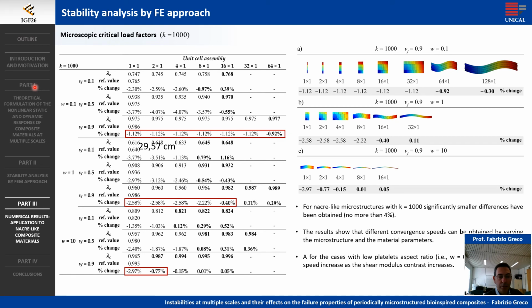For nacre-like microstructure with K equal to 1000, significantly smaller differences have been obtained. The results are reported in this table and show that different convergence speeds can be obtained by varying the microstructure and the material parameters. The figure illustrates this observation, showing the critical mode shapes for the composite with identical microstructure parameters and varying aspect ratio and unit cell assembly.